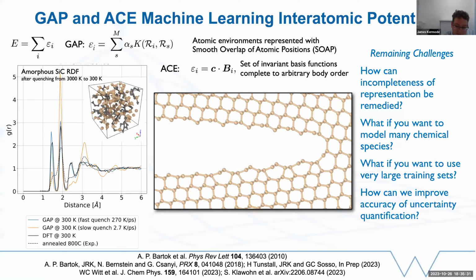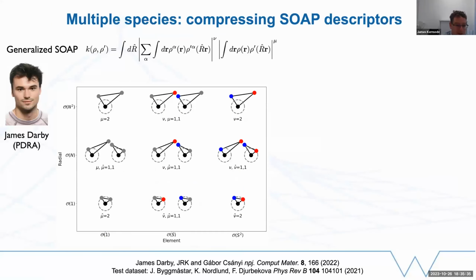So the first one is work by James Darby, who's a postdoc working with me at Warwick, who's done some really nice work together with Gábor Csányi on thinking about how we can apply these models to systems that contain many, many different chemical species. And what James has proposed is extending this SOAP descriptor so that we have a part which is the same as before, which is sensitive to individual chemical elements. So we're comparing a density of one environment with the density of another after rotating, and then we're integrating out the rotations. So this part, if you're familiar with SOAP, is really the same as before. But then what James is adding is a part here which doesn't care about chemical species. So these labels alpha here are for chemical species. This part of the covariance kernel is agnostic to elements. And then we get to choose these powers here to choose the appropriate balance between the element sensitive part and the element agnostic part, essentially.